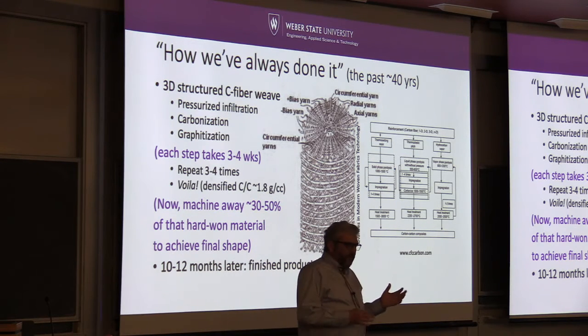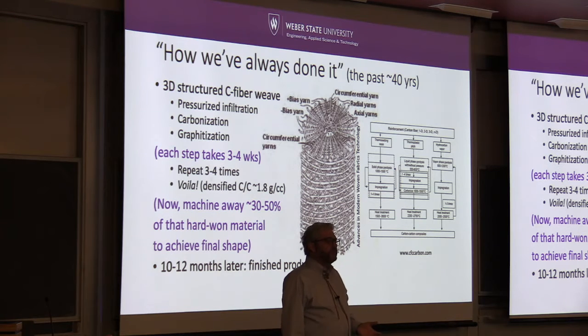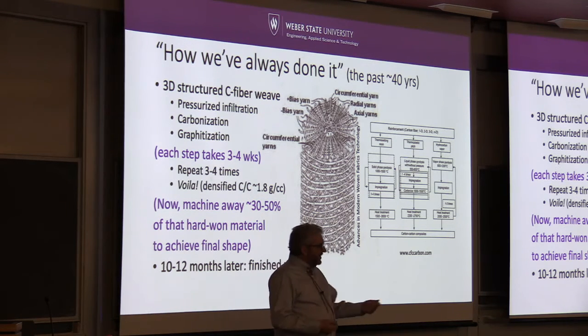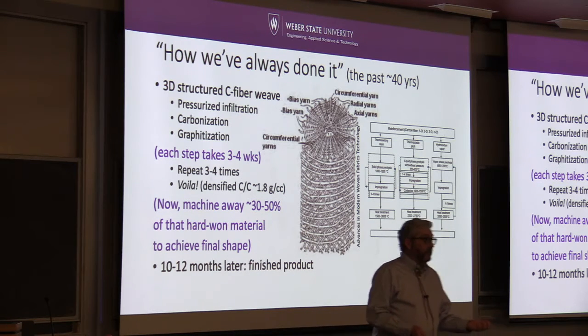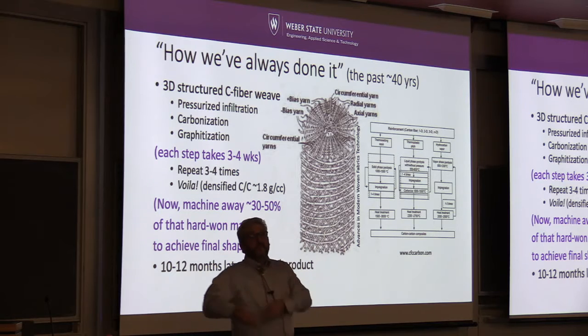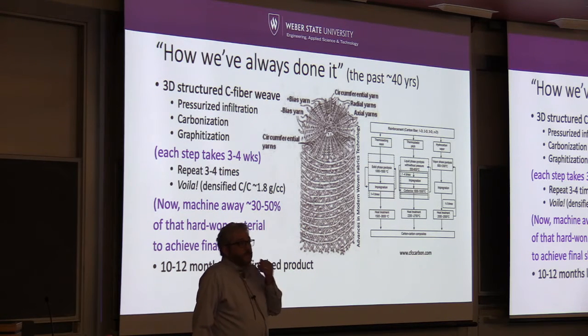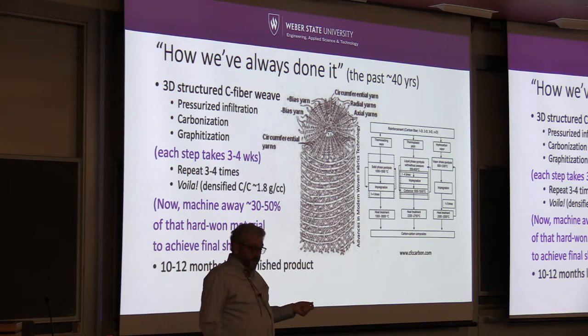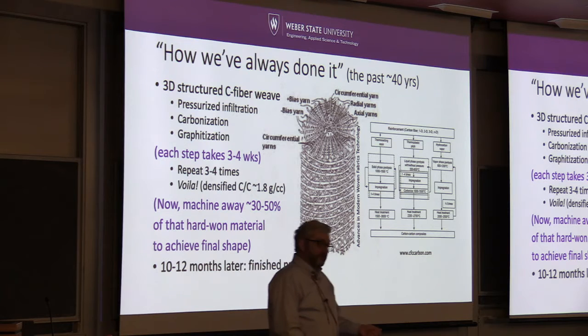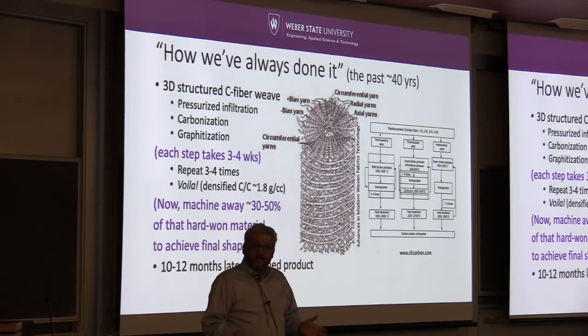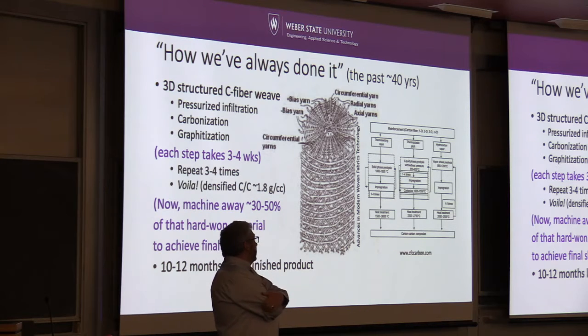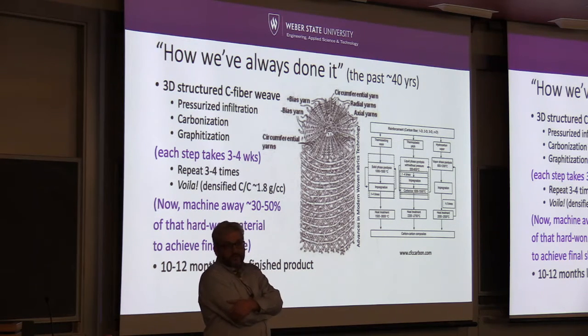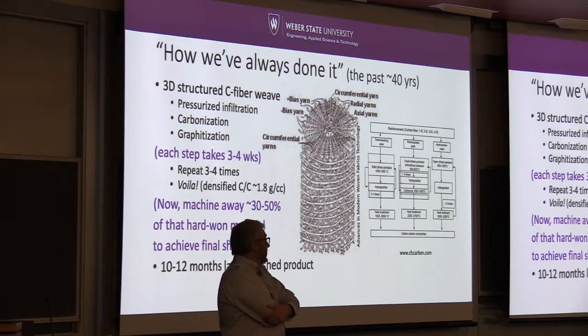And so one trip through, you get like 1.5 grams per cc, and then you pull it out and you look at it, and you're kind of this artisan: is the pizza done yet? And you go, no. So you go through the process again, and each time, every step of the process takes like 3 weeks, and every step takes this person who's been around for a long time to say, is it done yet? And so when it gets to 1.8 grams per cc, and that last little bit was really hard to come by, you're looking at 12 months for that billet to have gone through the process from weaving.